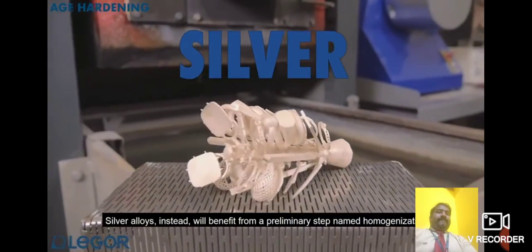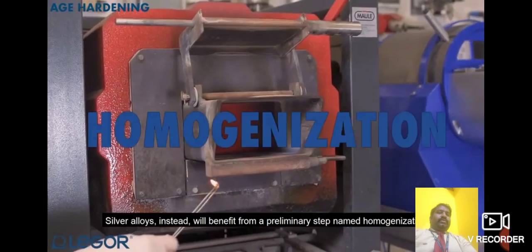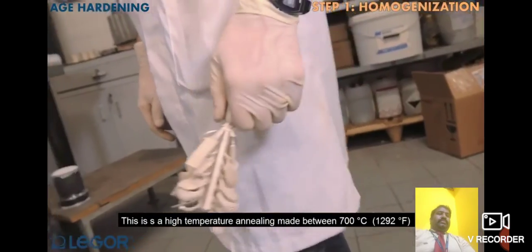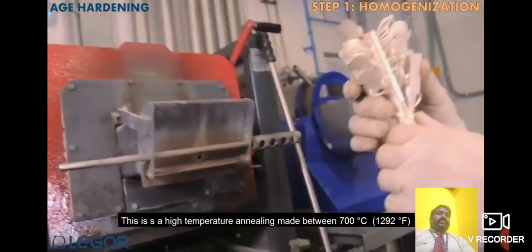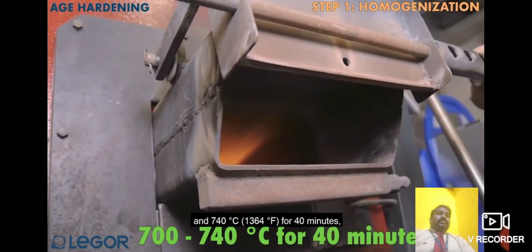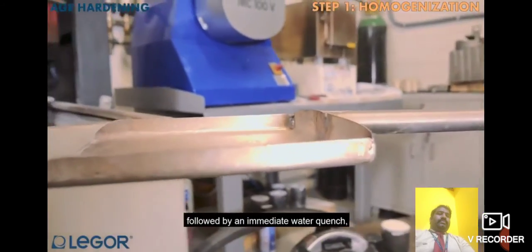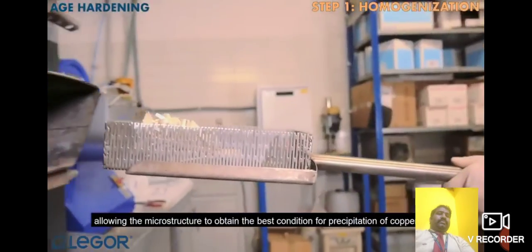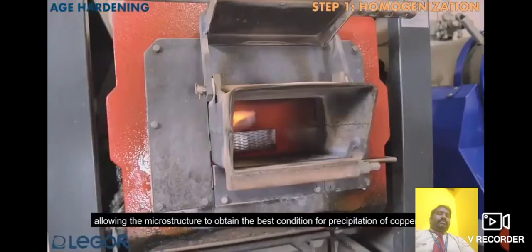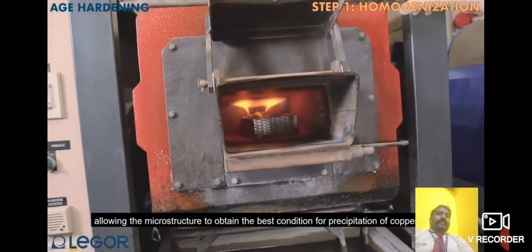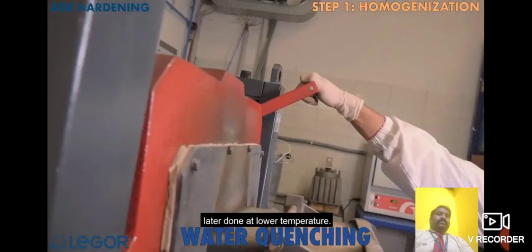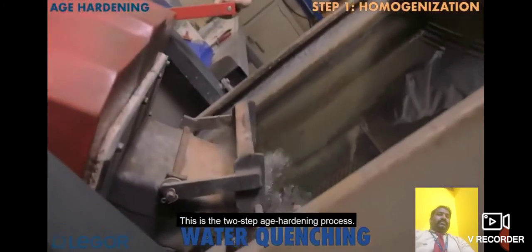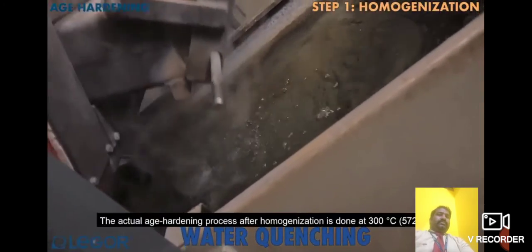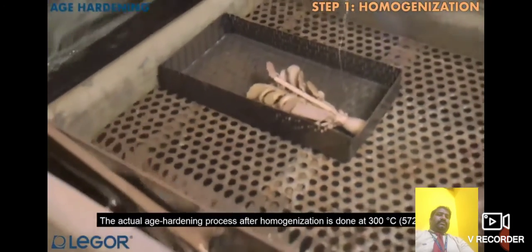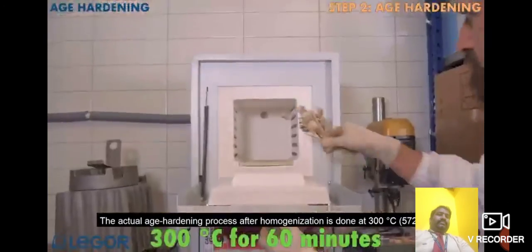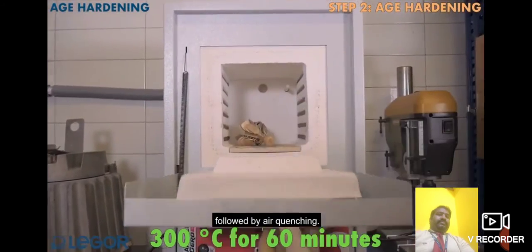Silver alloys instead will benefit from a preliminary step named homogenization. This is a high-temperature annealing made between 700 and 740 degrees Celsius for 40 minutes, followed by an immediate water quench, allowing the microstructure to obtain the best condition for precipitation of copper particles in the silver matrix, later done at lower temperature. This is the two-step age hardening process. The actual age hardening after homogenization is done at 300 degrees Celsius for 60 minutes, followed by air quenching.